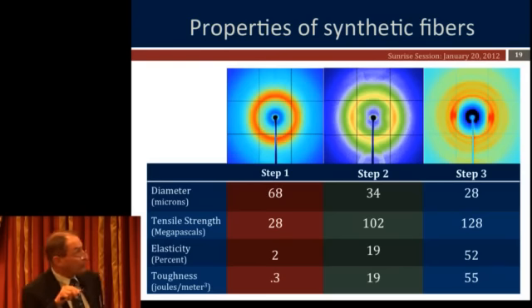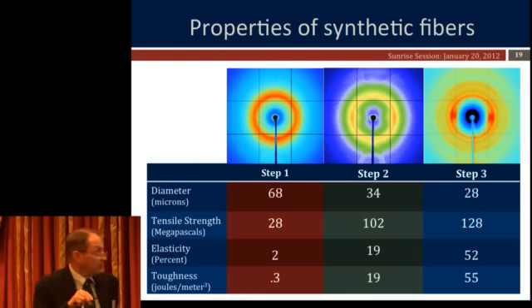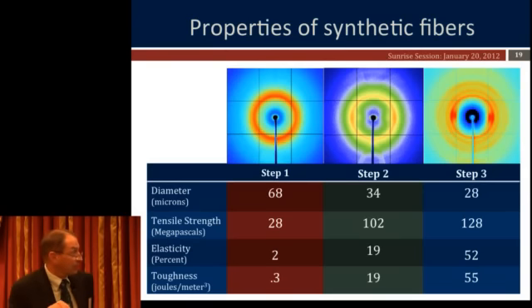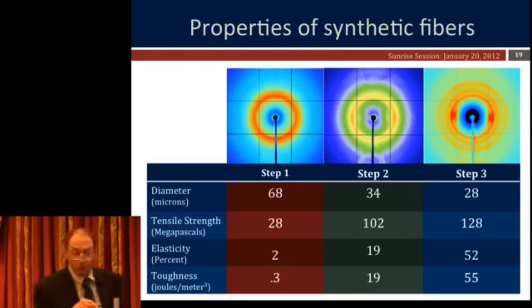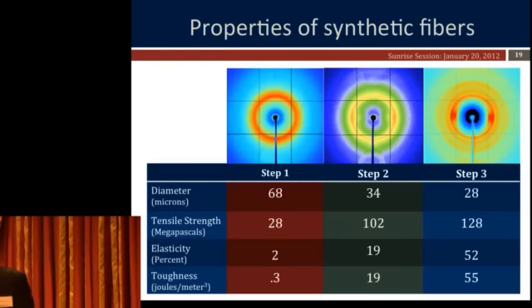So this is what it looks like when we first spin it. It's about 68 microns in diameter, tensile strength's not so good, elasticity really sucks, and overall toughness is not very good. What you see in the X-ray is this very pretty ring with absolutely nothing there, which means that you have no real structure. That is, this thing is amorphous, which means nothing there.